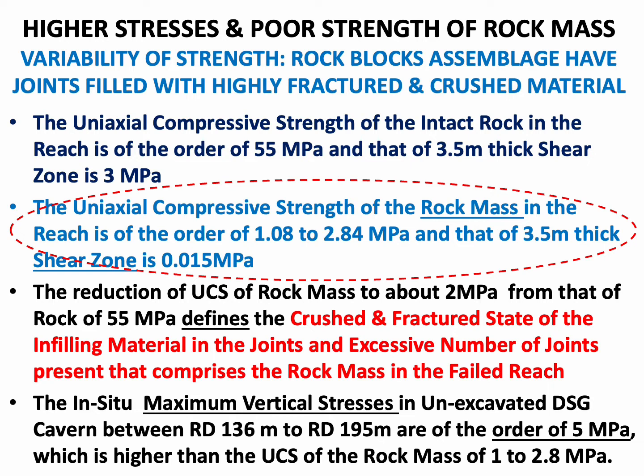So there is a huge difference, or variability, of compressive strength in the rock mass as compared to the intact rock constituents of it. The reduction of UCS of rock mass to about 2 MPa from that of 55 MPa defines the nature of the crushed and fractured state of the infilling material in the joints, and the excessive number of joints present that comprise the rock mass in the failed reach. So what brings the UCS from intact rock of 55 MPa to that of rock mass of around 2 MPa is the existence of crushed and fractured infilling material in the joints, and the excessive number of joints. So they together bring the rock mass to a strength of merely 2 MPa.